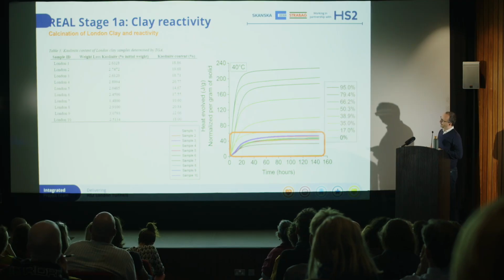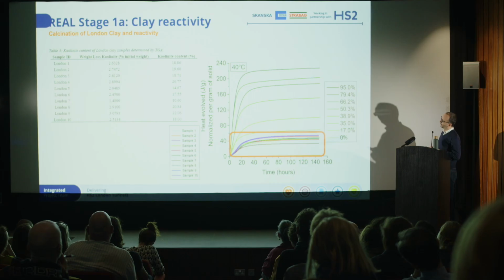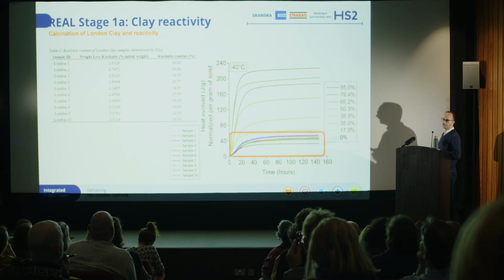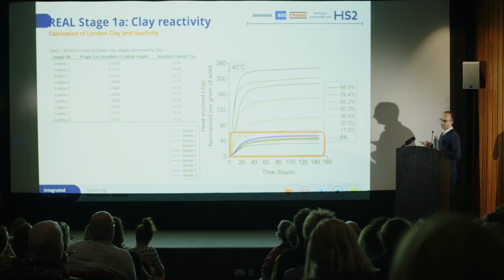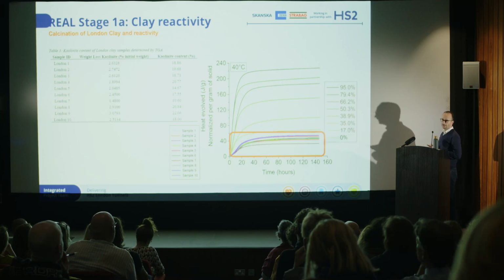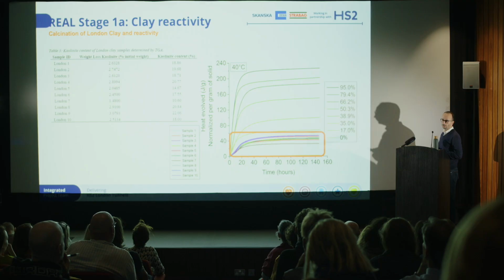Now, we started testing. One of the measures for reactivity of clays is the kaolinite content. So the higher the content, the higher the reactivity of the clay. Normally, in the industry, we had kaolinite content of 90% as metakaolin being used in concrete, but no one has used something lower than that or had looked into this.